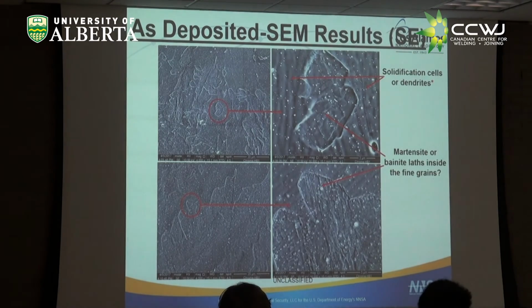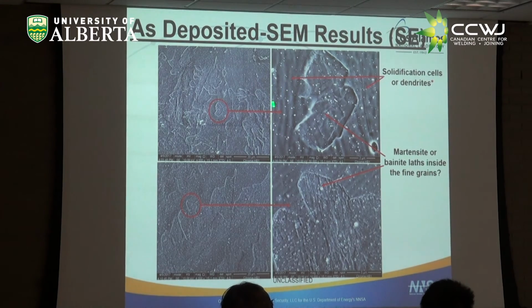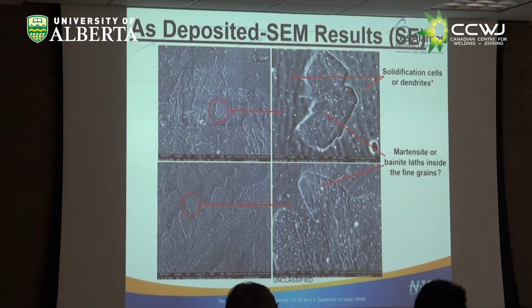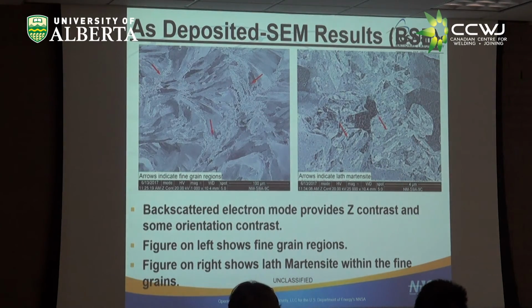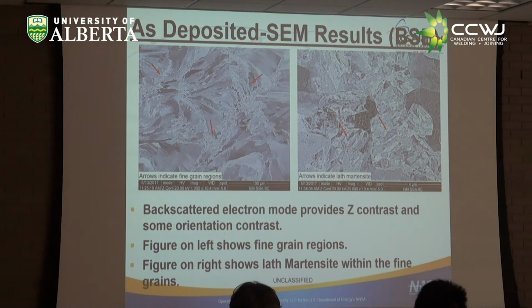But we can see that here as well, around that little region, solidification structure. And then within these regions here, you see this lath-like stuff, right? It's reminiscent of martensite or bainite. But it's only within that little circle, or this little region here and here. Otherwise, it looks like solidification everywhere else. Okay, still lots of confusion, what's going on. Next, we can do backscatter electrons. So this shows more Z contrast, but you can still identify, I hope you guys can see, some of the things again that look like lathy regions in there as well.